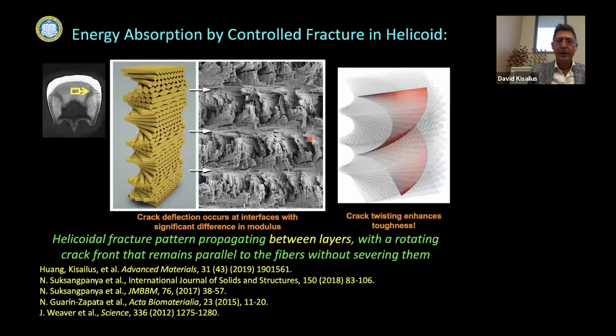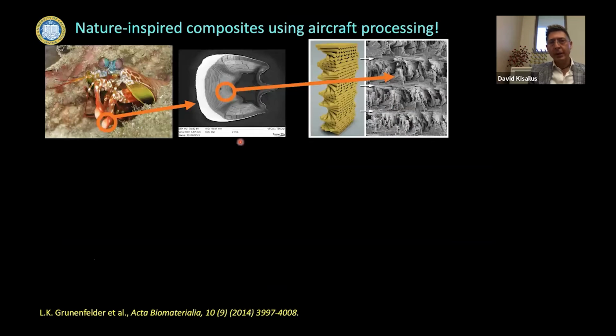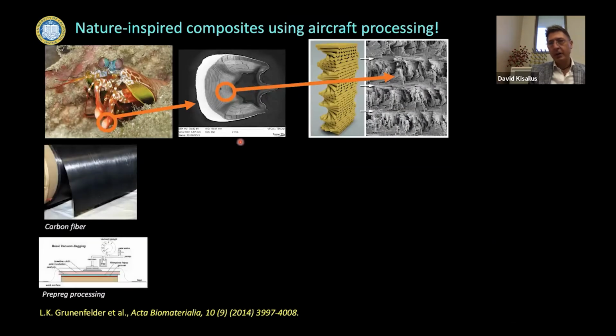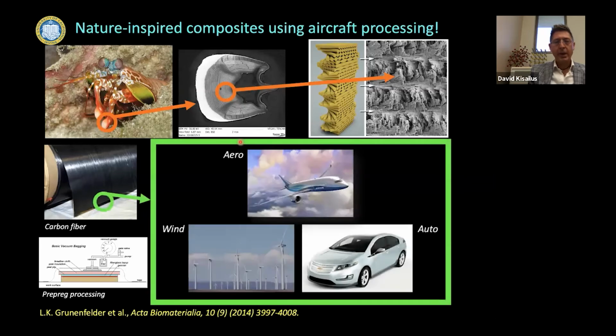And so again, going back to this helicoidal structure, this ability to localize damage is due to the ability to have crack deflection, but also crack twisting at these interfaces that provide that additional toughening. So we took that design and said, okay, let's take that Bouligand or helicoid structure. Instead of using alpha chitin and hydroxyapatite, we replaced it with carbon fiber, unidirectional carbon fiber tapes, and made helicoidal composites. And now we have a number of programs for both aerospace, wind, and automotive composites.